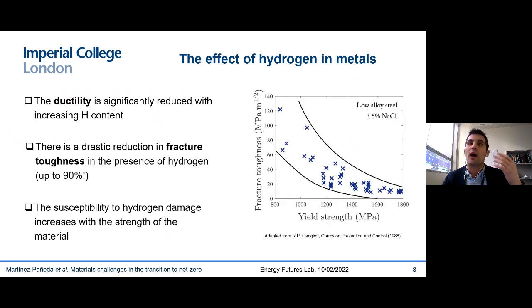The susceptibility to hydrogen damage increases with the strength of the material. You see here fracture toughness in a given hydrogen-containing environment, so this is similar to seawater. And then you see that as you increase the yield strength of your material, your fracture toughness goes down up to the point that for these high-performing alloys, these high-strength alloys, hydrogen-assisted fractures occur at toughnesses that are below 10 megapascals per square root meter, so almost like a ceramic. We like metals because they are ductile, but hydrogen makes them very brittle.